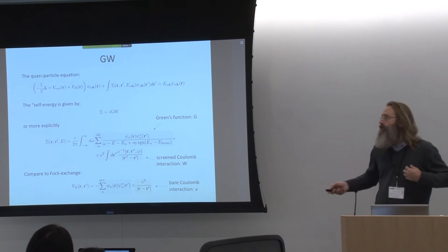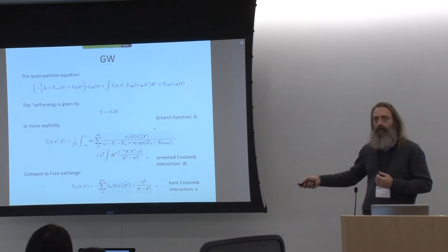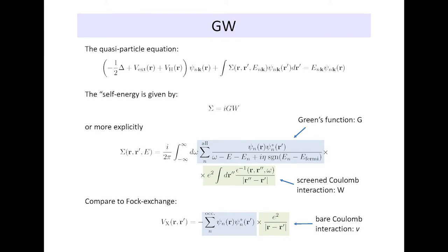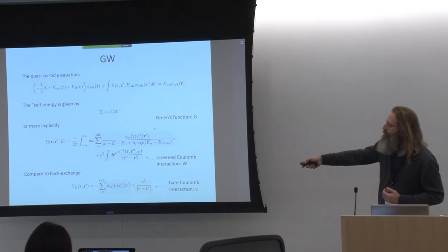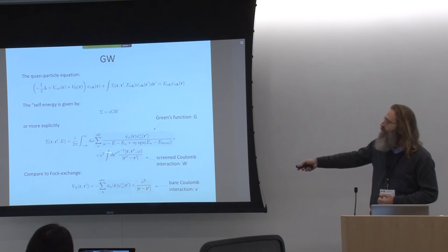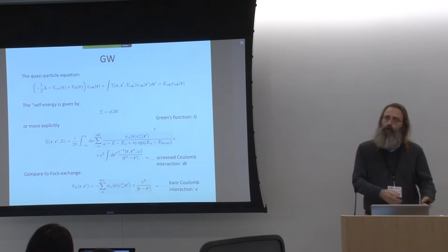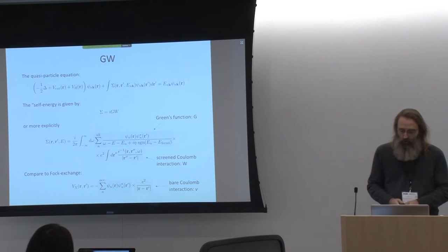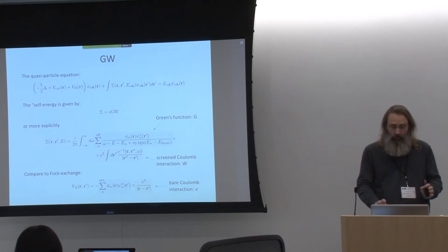And that is a connection that you could make, for instance, to hybrid functional theory, right? Because in hybrid functional theory, we say we use a quarter of this. So this would be like using a fixed screening, saying we screen this at every point r and r prime and every frequency with the same amount, with one quarter. And here, of course, we have an object that is material dependent, because we compute this for every system. So it's not a fixed screening, but it tries to take into account the true dielectric properties of our system within an approximation.